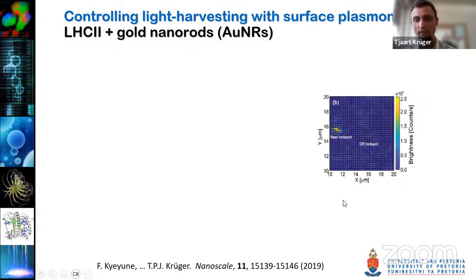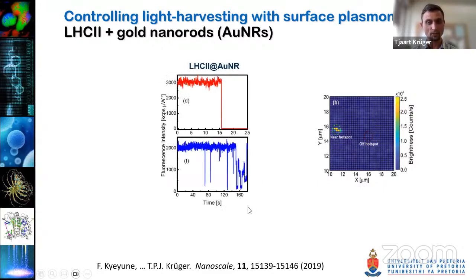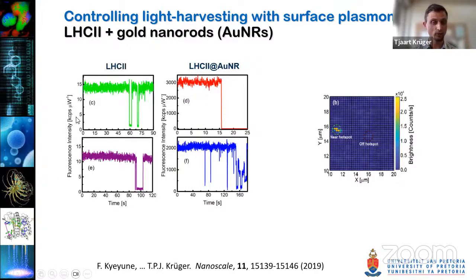So what you would typically find is that when LHC2 is far away from a hotspot, you would see relatively weak fluorescence. But when it's near or inside a hotspot, you will see very strong fluorescence. And this is illustrated here. So LHC2 in a hotspot, you see a significantly enhanced fluorescence intensity compared to LHC2 that is far from a hotspot. So 2 orders of magnitude increase in the fluorescence intensity.